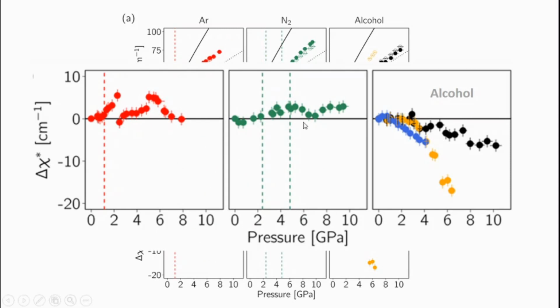In the alcohol experiment, chi evolves very differently, and that for the three experiments we have done. After realizing that in one of the experiments the system partially unbinds from the substrate during compression, we were able to evaluate that, in addition to the compressive effect, there was a charge transfer effect which is more important for the top graphene layer in contact with the alcohol medium than for the bottom layer.